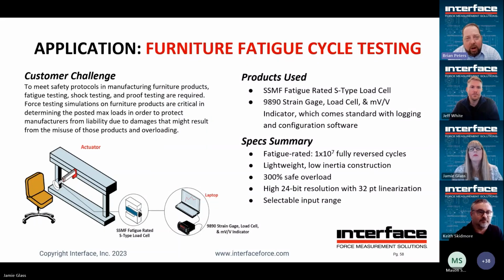Secondly, if you are often getting into that overload range and you can't avoid it, best thing to start tracking would be your zero balance. If you start to see that zero balance shift, then that means you started to do some permanent physical damage, and you started shifting up that output curve. It may still meet spec, as Keith said, but if you shift it too much, it may no longer meet the spec through the full capacity range.